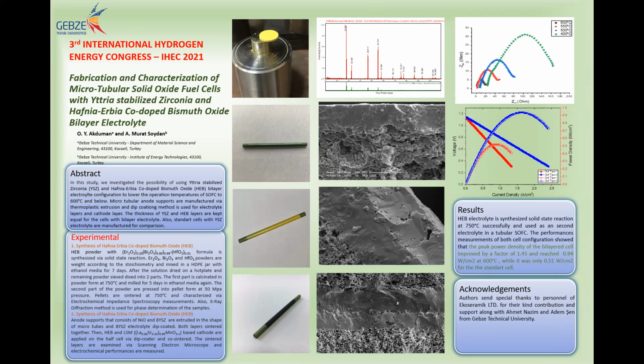Okay. Yeah. Erbia increases the number of the oxygen vacancies, and Hafnia is there to stabilize the phase for the long term. Because these bismuth-based materials show aging or phase change during their operation, and Hafnia is basically there to stop it and make it more stable.